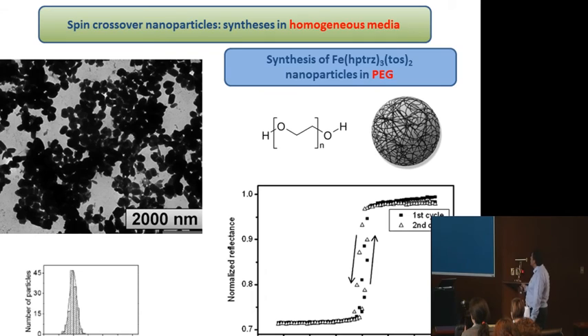For example, here I will present some results concerning homogeneous media. Homogeneous media means that you have only one phase. In this case, you just add a polymer to again try to limit the growth of the materials. Just using this polymer, it's possible to obtain homogeneous particles, but quite large particles. It's not possible, like with reverse micelles, to have small size. You limit the growth, but you have quite large nanoparticles. Of course, with such a size, you have the same property as the bulk, so you have a hysteresis loop centered at 310 K.